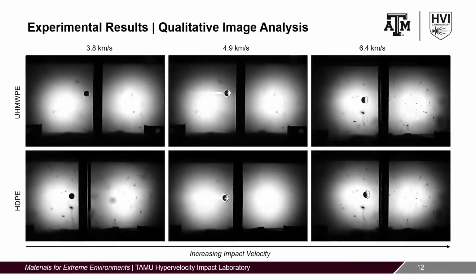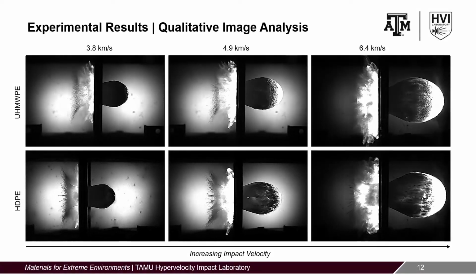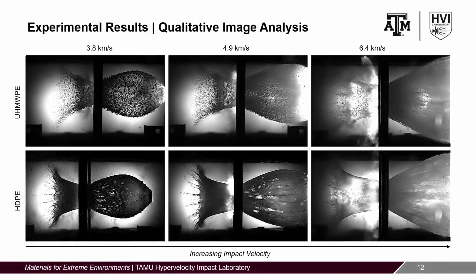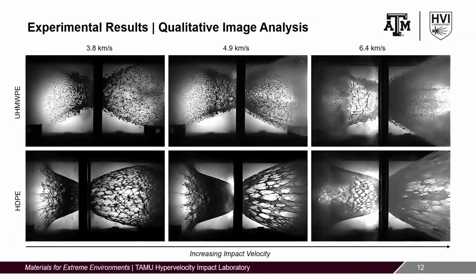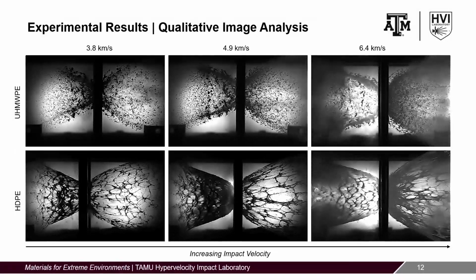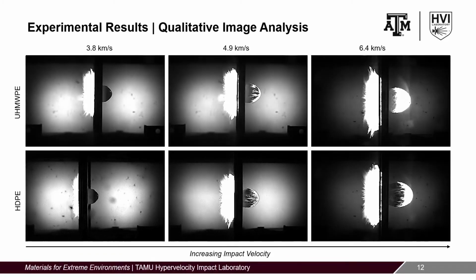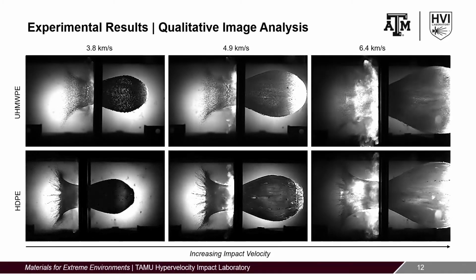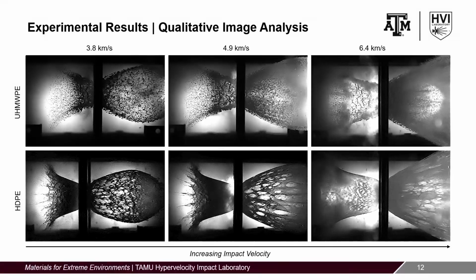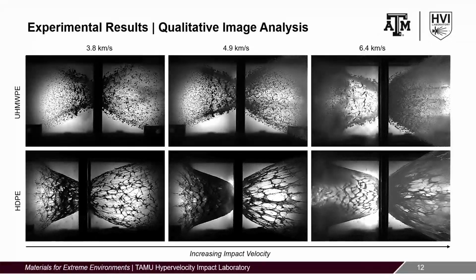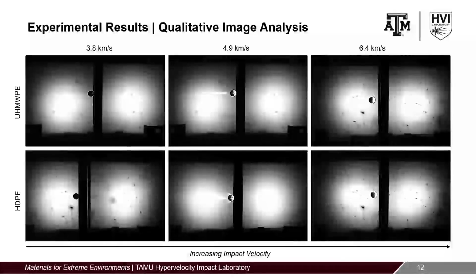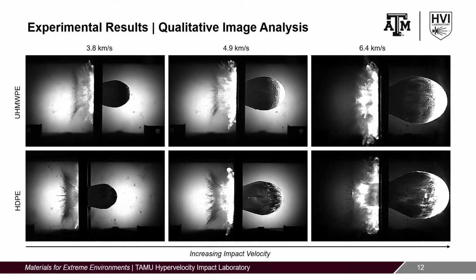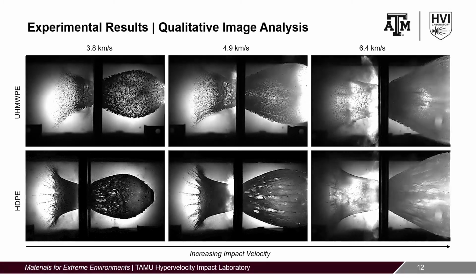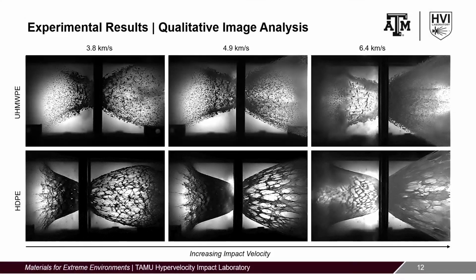These videos display high-speed images at 1 million frames per second of hypervelocity impact events for various velocities across the tested regime. The tests shown on the top are of ultra-high molecular weight polyethylene, and the tests shown on the bottom are of high-density polyethylene. The impact velocity corresponding to each video increases from left to right and is provided at the top of the figure. Ultra-high molecular weight polyethylene fragments into finite particles, while high-density polyethylene displays apparent bulk melting and condensation during debris cloud expansion for the same impact velocity and projectile.